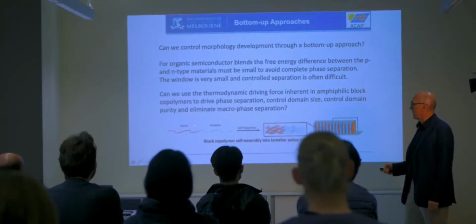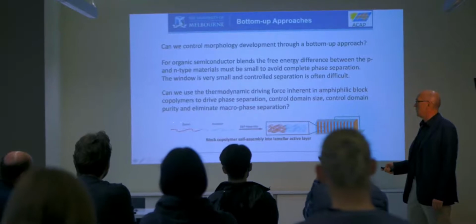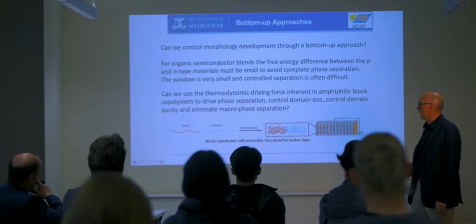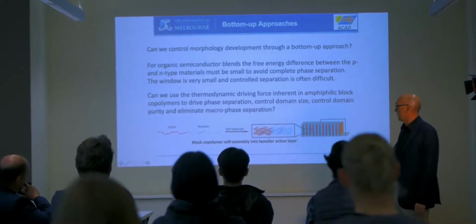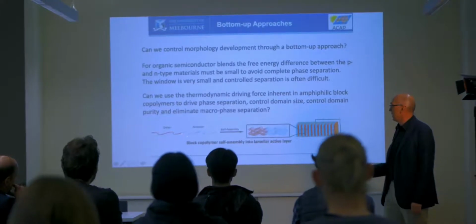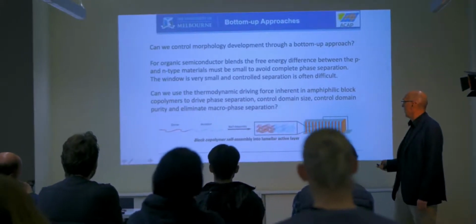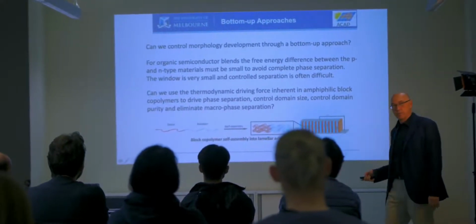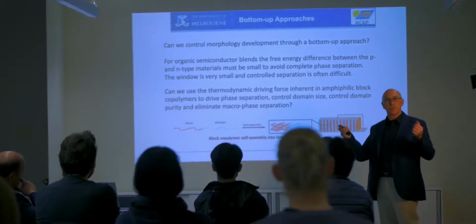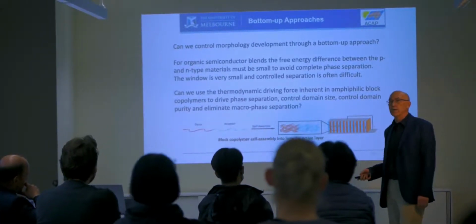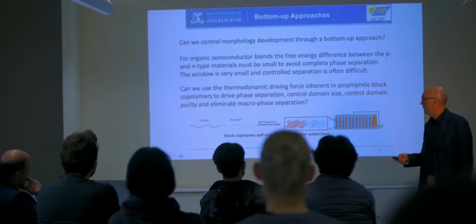And so if we basically have a donor, the P-type semiconductor, and the acceptor, the N-type semiconductor, now we tie them together, we can self-assemble, and we should get an ideal type structure. So we've used a bottom-up approach to control the phase separation in these materials.